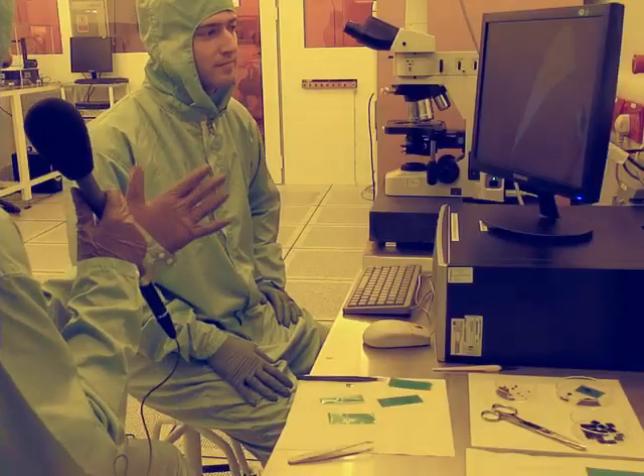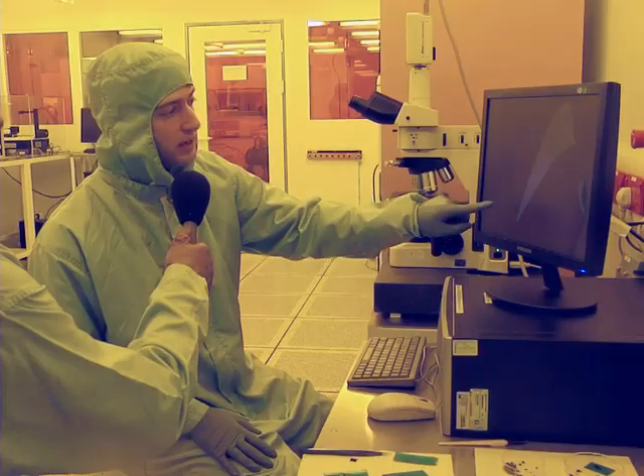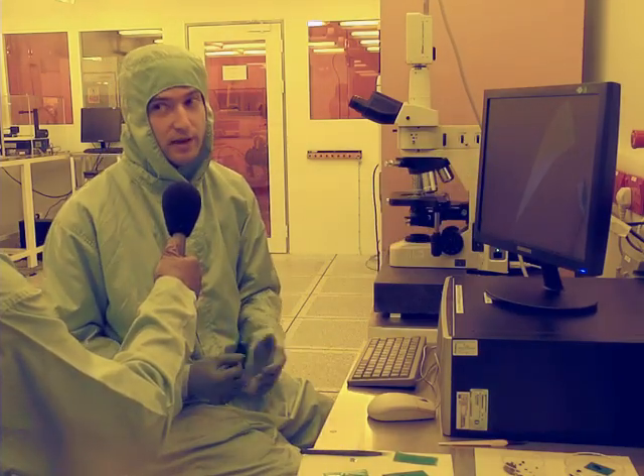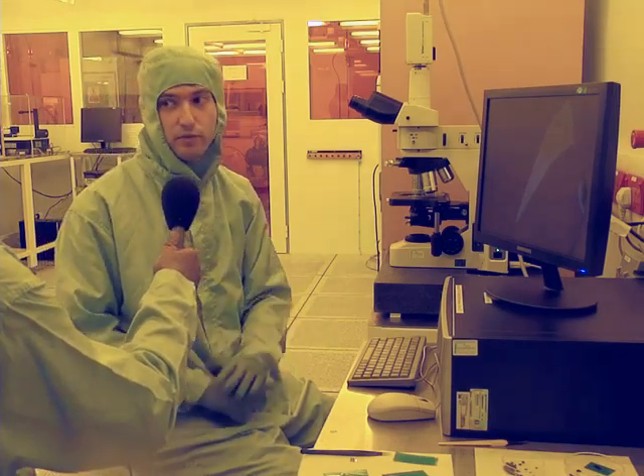So what are we seeing now in front of us? There is quite a variety of actual colours and layers. What you see on the screen — this triangle shape — is just one single layer, while together with it there are other materials which are thicker. This yellowish stuff is essentially graphite, which means a very large number of layers. And you can see on the side of the screen there is a purple region, which represents very few layers.